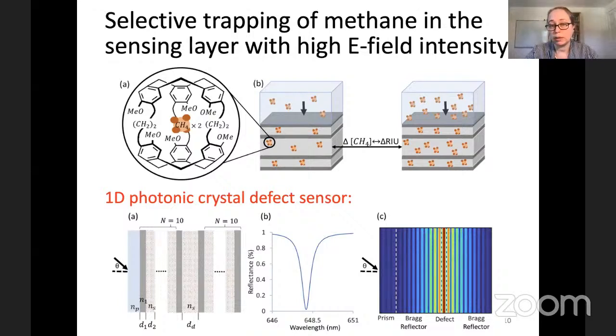So what we did, we re-engineered the sensor, and instead of using surface plasmon resonance, we built a simple photonic crystal defect sensor, which also features a resonant mode at a certain frequency, which can be tunable by design. But this mode, as you can see by the frequency or wavelength bandwidth, is significantly higher quality. It's a narrow bandwidth mode that is easier to track. If it moves just a little bit spectrally because of changes of the refractive index, this can generate a very large difference in reflected intensity at a single wavelength. So if we just excite the system and monitor it at that single wavelength, we don't need all the additional complexity in the sensor.